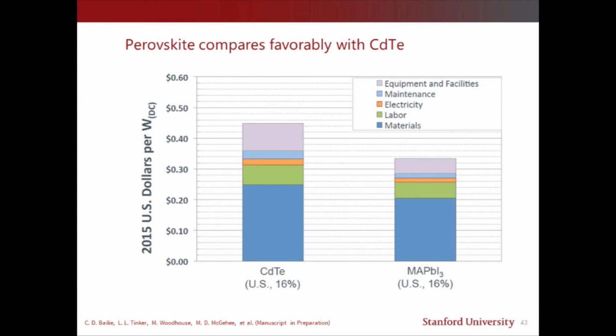Comparing cadmium telluride to the perovskite under apples-to-apples conditions, meaning they were both manufactured in the same place and produced the same efficiency, would save about 10 cents per watt from the cadmium telluride module. Since the module only costs 50 cents to begin with, saving 10 cents per watt is a significant amount.